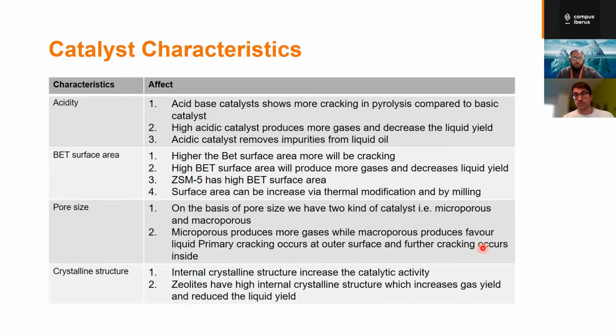Pore size is also very important. On the basis of pore size, there can be microporous structures or macroporous structures. Microporous structures have small pores and they produce more gases. But if you have macroporous structures, they form liquid primary product at the outer surface. But if it goes into the pore itself, then you have more cracking inside, so you have lighter compounds. The crystalline structure of the catalyst also improves the activity of the catalyst. Zeolites basically have a good high internal crystalline structure, but at the same time that also boosts the gas yields and reduces the liquid yields.